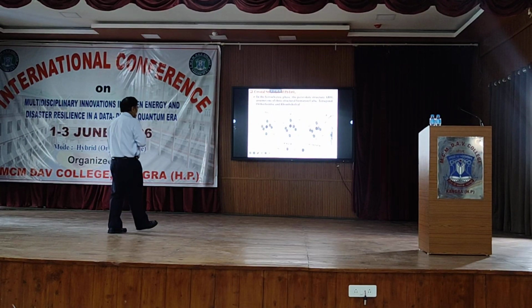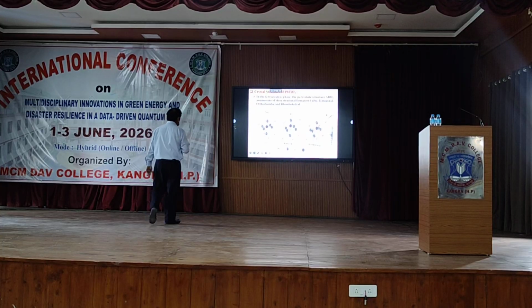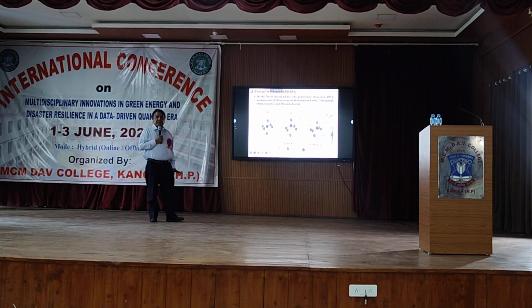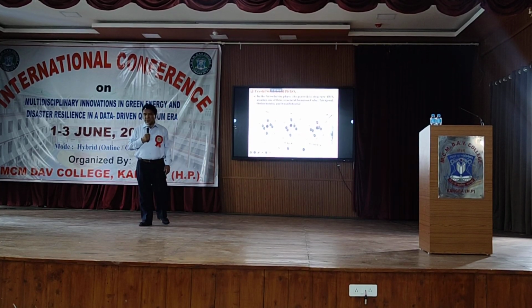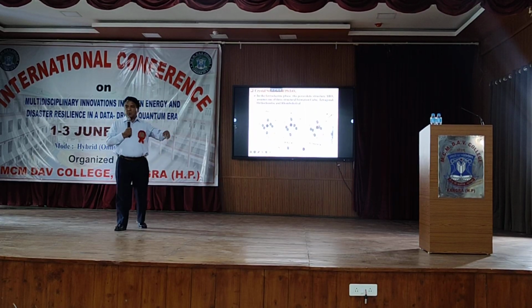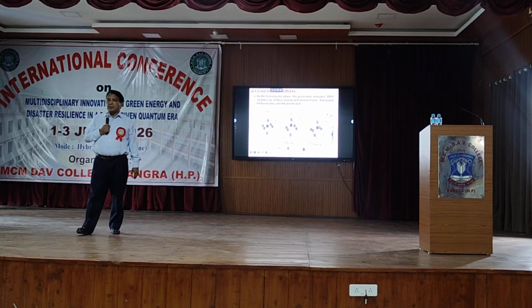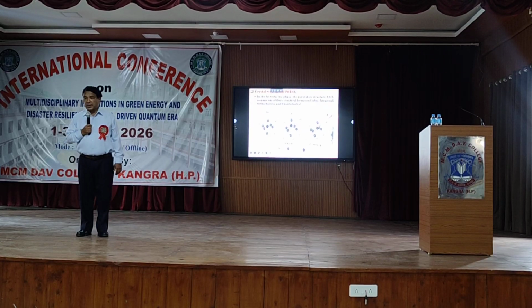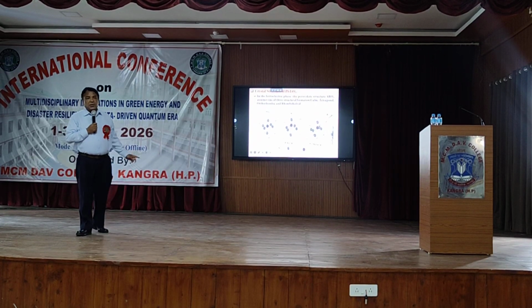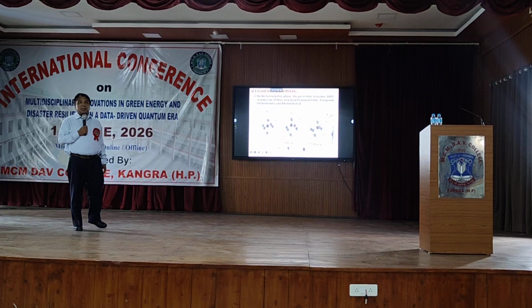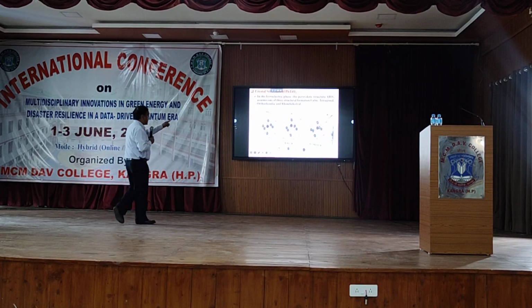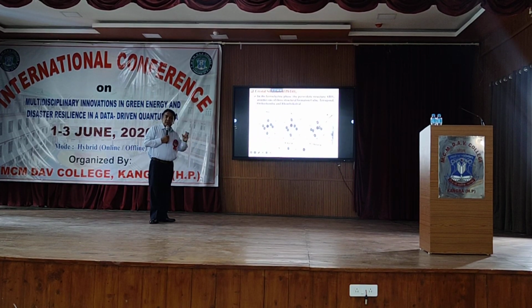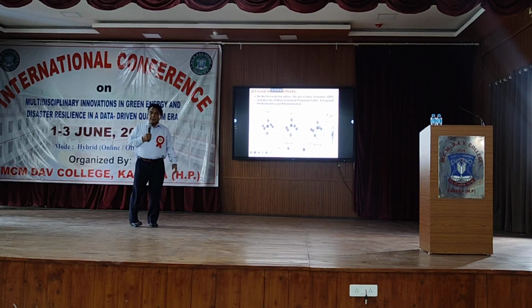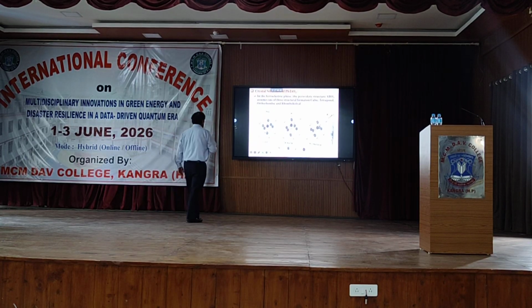And these dipole moments are very critical to decide ferroelectric, piezoelectric and pyroelectric properties. Such structural transformation can be obtained either by applying pressure, or by tuning the temperature, or by making substitution in the ABO3 and varying the concentration of the element. One can go from cubic to tetragonal to rhombohedral to orthorhombic in this structure.